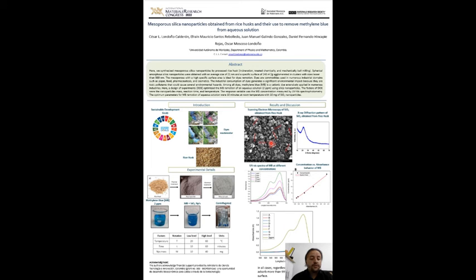The optical absorption spectra for methylene blue samples at different concentrations were recorded. The maximum observed absorption is around 664 nanometers and it is in agreement with previous reports. From the figure, it's clear that the absorption spectrum is proportional to the concentration of the dye. The concentration of the methylene blue solution as a function of the absorbance value at 664 nanometers was also recorded. From this adjustment and by means of linear regression, the equation that relates absorbance to concentration was obtained. With this equation, the concentration value of an analyzed sample can be predicted 99% based on its maximum value of